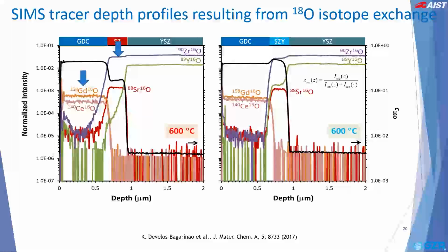In addition, we see that the yttrium signal shows a broadening from the YSZ region into the strontium zirconate region, indicating that the yttrium has diffused. This suggests that in the vicinity of the strontium zirconate interface, there is some amount of yttrium in the composition of the material. On the other hand, the concentration of the 18O tracer normalized using the equation shown is plotted as black curves in the plots.